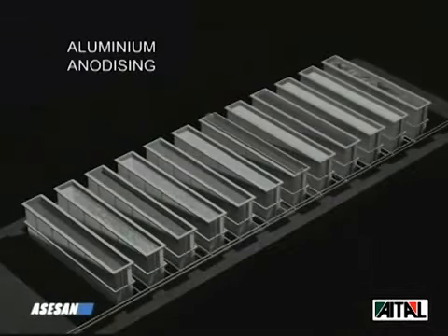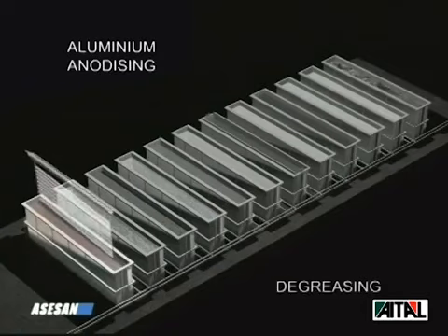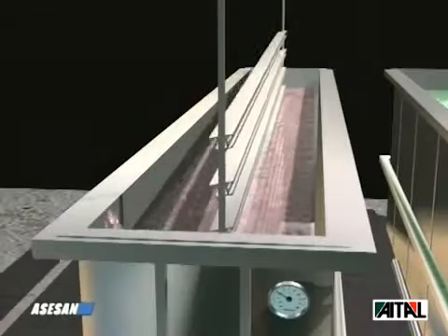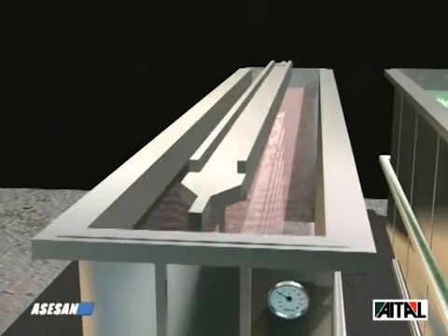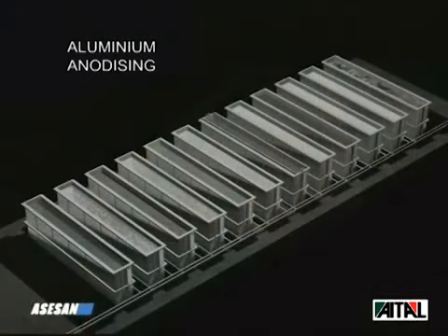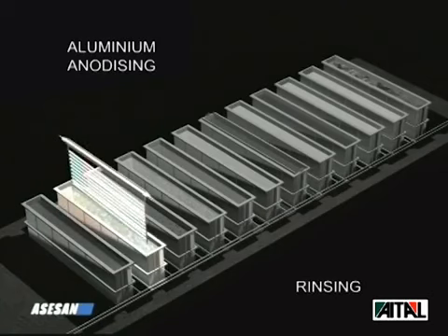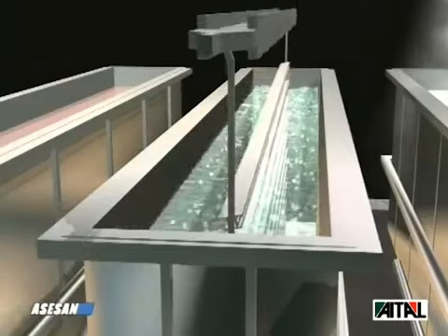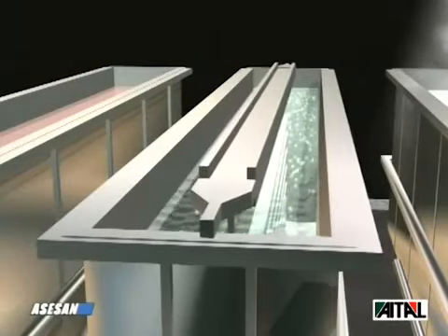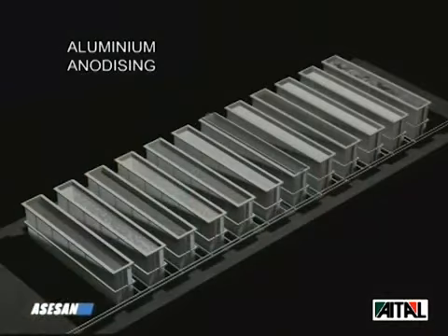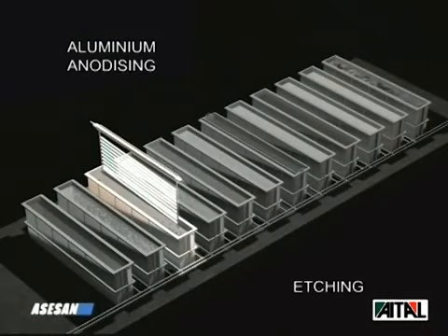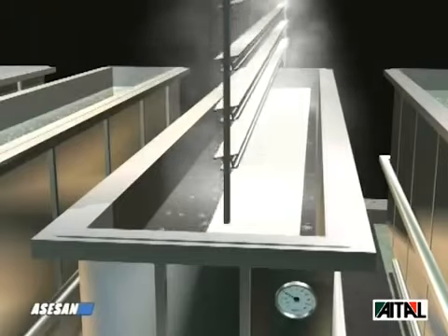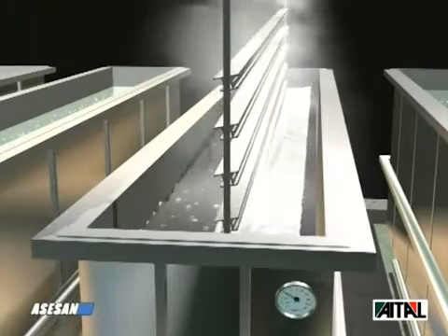The steps in this process are as follows. First of all, the surface to be anodized is degreased to eliminate oils and greases deposited on the surfaces during previous processes. It is then rinsed with abundant water. After, an etching solution or chemical brightening is used to eliminate the natural oxide and make the surface appearance more uniform.